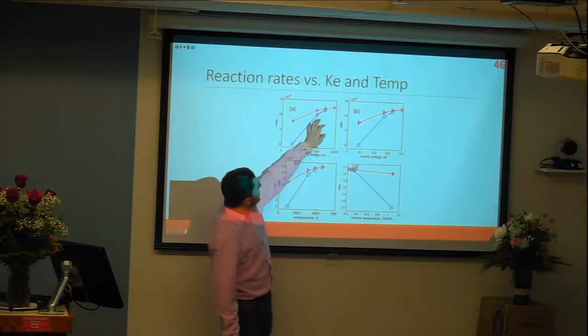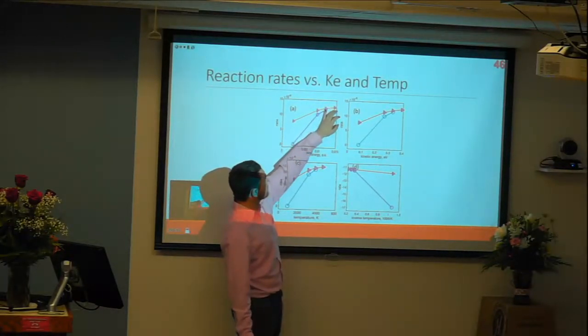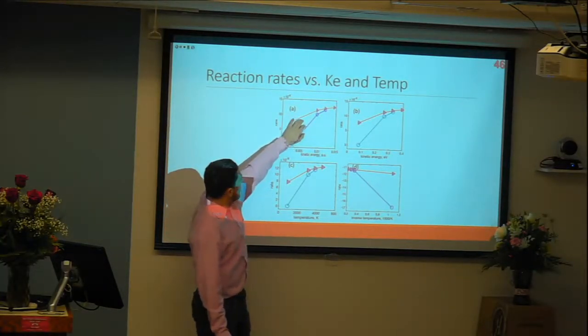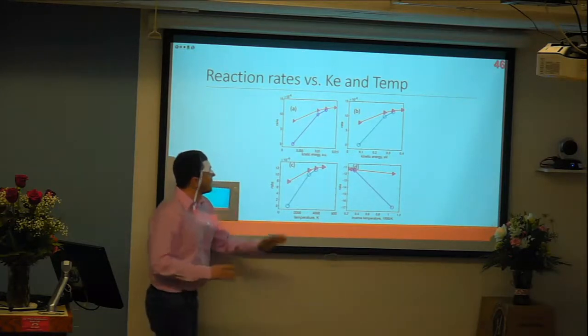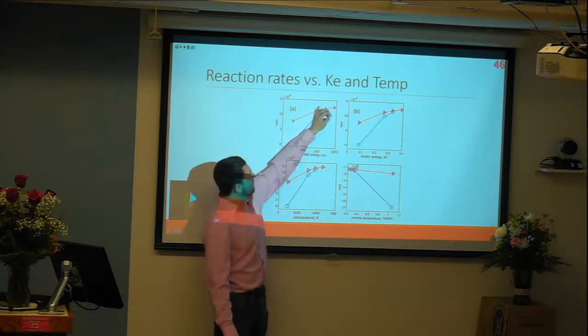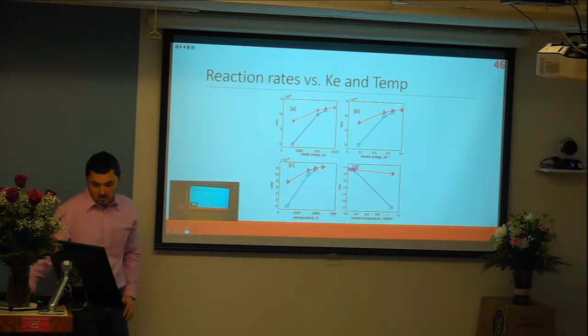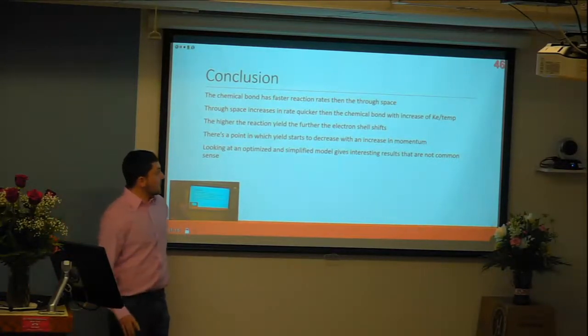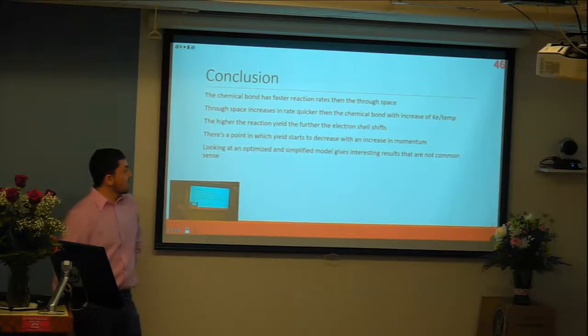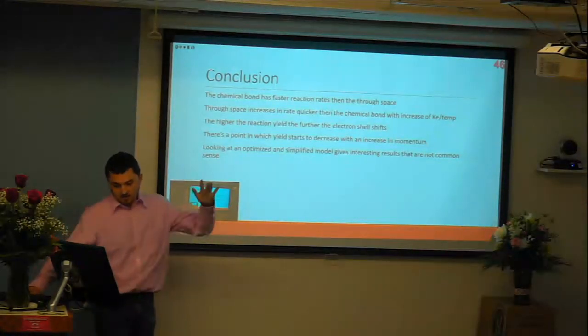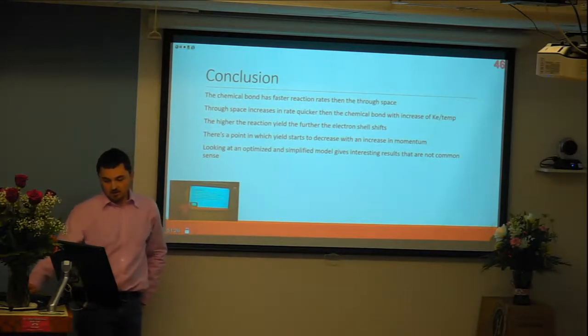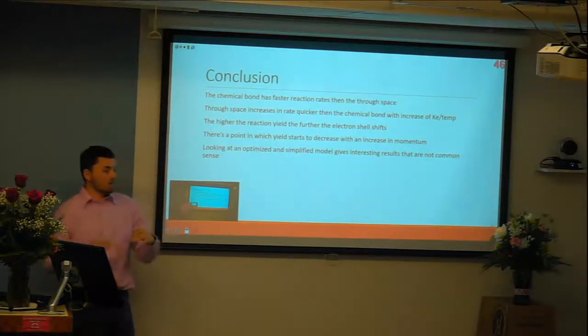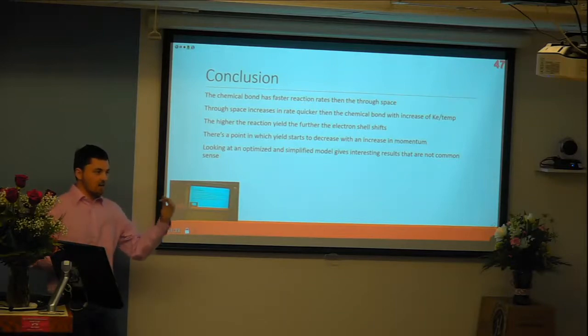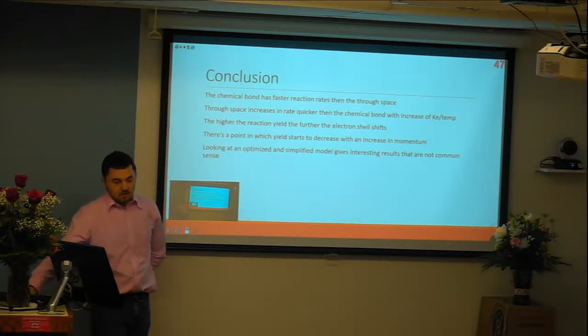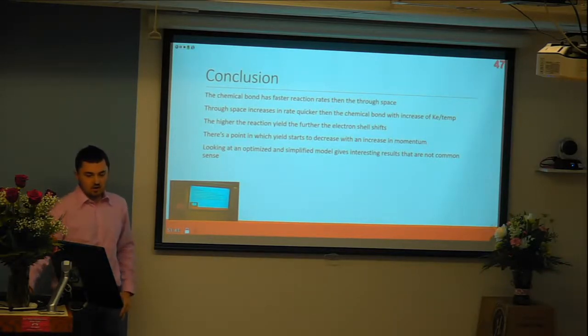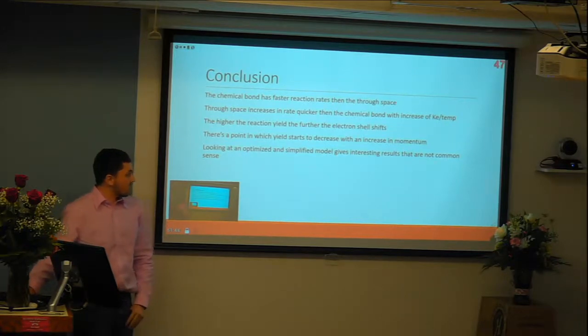And as you increase, we'll see a quick increase in reaction rate for the through space, which is circles, and these triangles are the chemical bond. And you can see a faster rate increase, and the chemical bond is just faster overall through the whole scenario. So in conclusion, the chemical bond has faster reaction rates than the through space, but the through space has a quicker reaction rate increase. Higher reaction yields yield further electron shifts, and there's a point at which the yields start to decrease because the momentum overpowers and the electrons are able to jump back and forth between the donor and the acceptor. We're looking at a very simplified version of this scenario due to just a learning experiment.